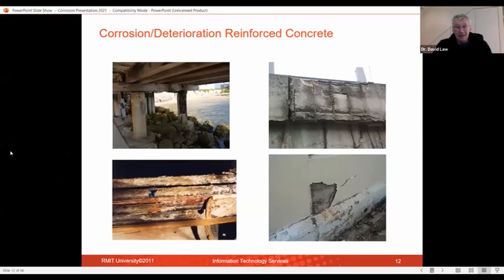This is the sort of thing that you see on the old structures, and I've just got some examples here of what happens when you have corrosion of your reinforcement. The top one here is a marine structure. The bottom one is actually also on a bridge where you've got corrosion. This is a bridge in Central Europe, and that's due to de-icing salts again. The bottom one is actually due to water leaks that are coming through, and they are then initiating the corrosion inside the concrete.